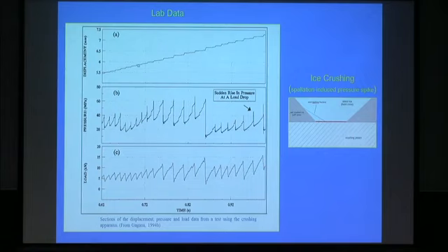Oh yes, and this is the actual displacement of the ice towards the platen. Due to the compliance of the ice and the platen that Kai referred to earlier, even though the nominal crushing rate is linear, a fixed rate, the true crushing rate has this stepwise type pattern.